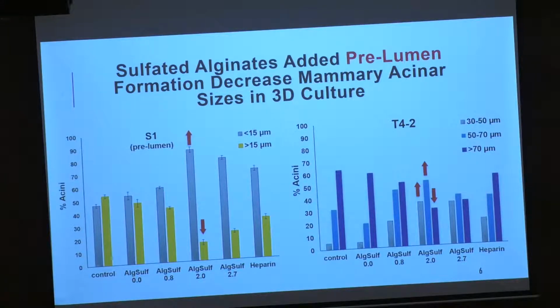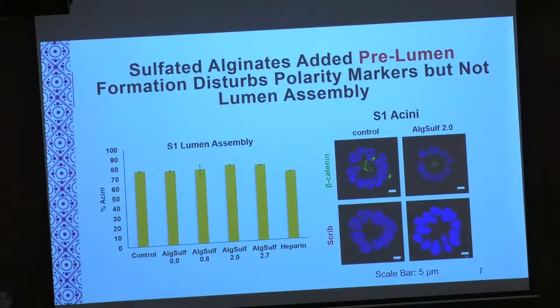We wanted to see if these alginates affect the capacity of the acini to form lumen, and fortunately, they did not. So all the cells with all the conditions were capable of forming lumen, but some of the polarity markers were redistributed from the apical side to the basal side and apicolateral side, both beta-catenin and SCRIB, which are polarity markers that are commonly tested in these cell lines.